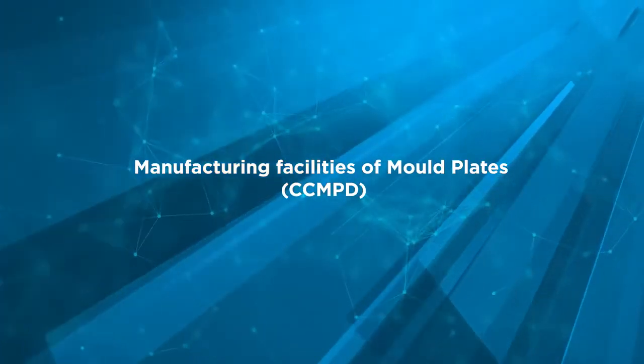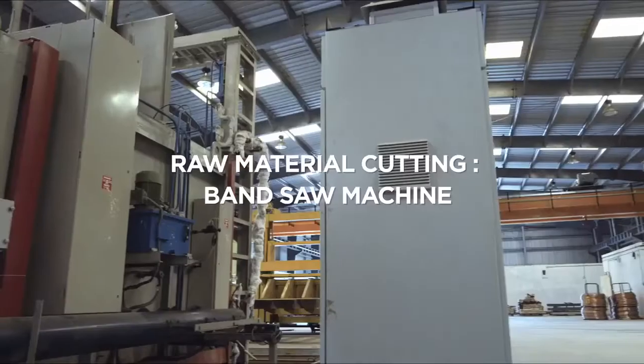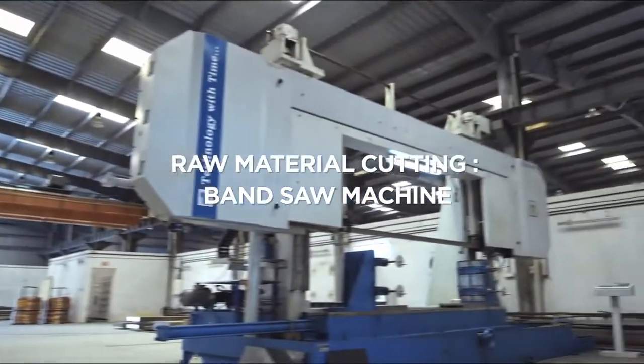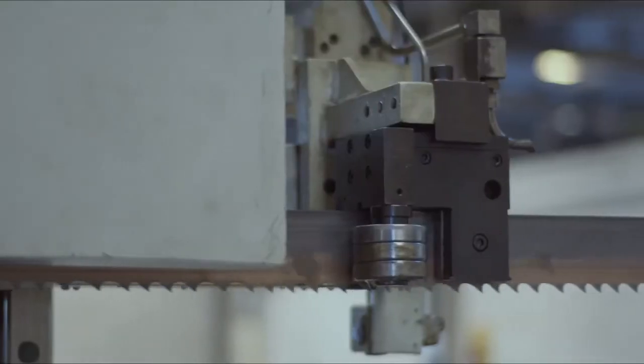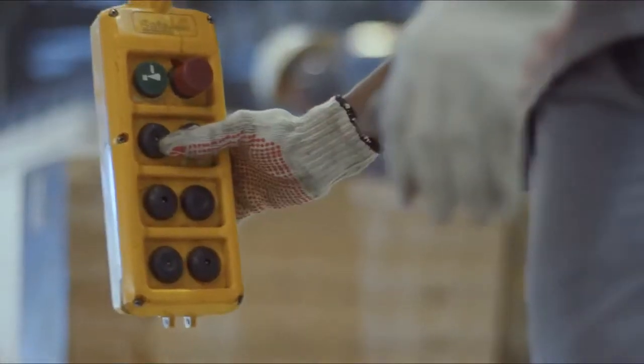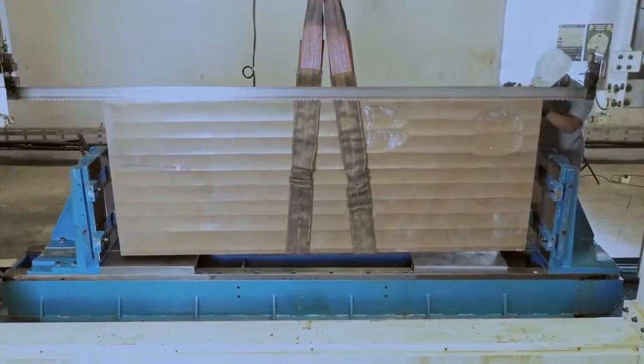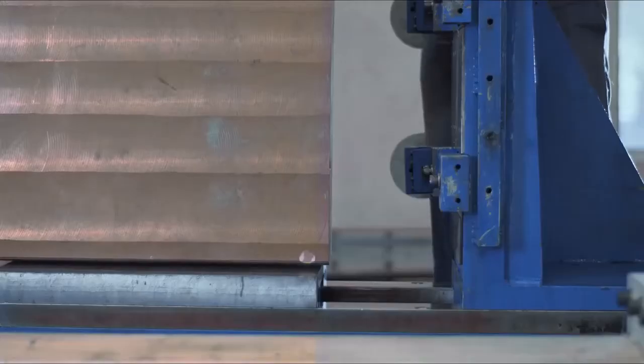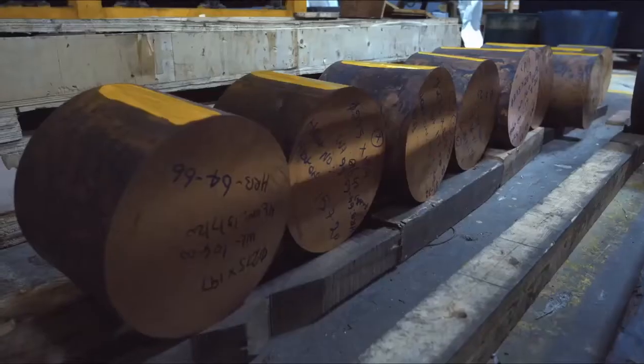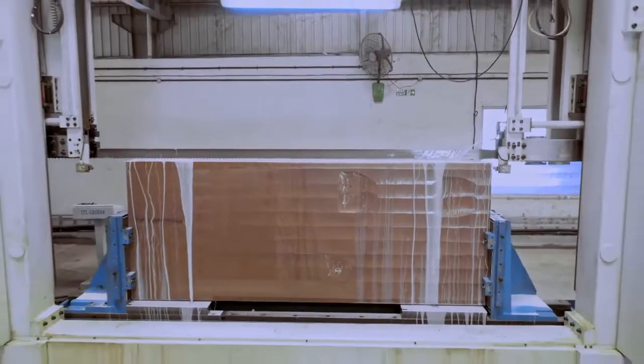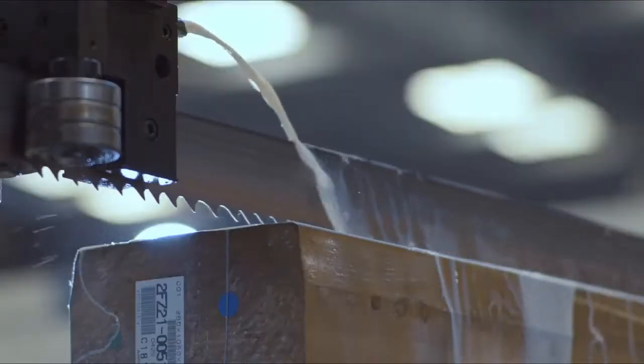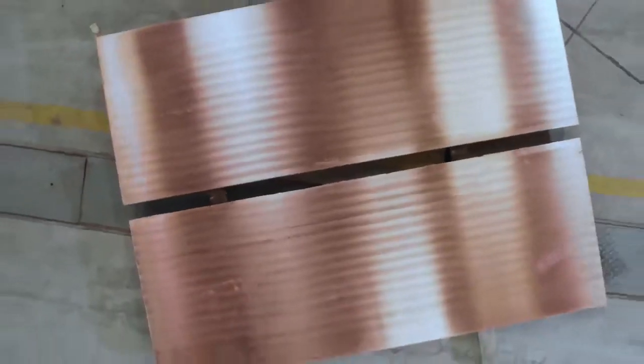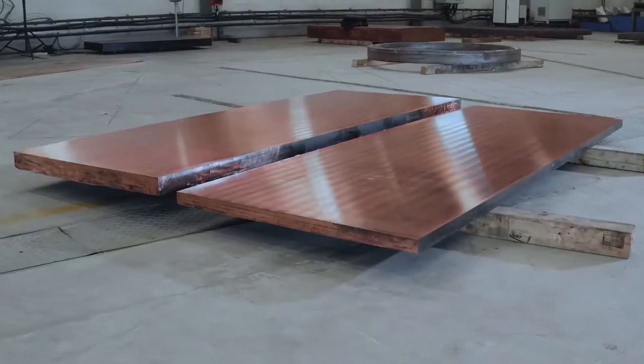Manufacturing facilities of mould plates, CCMPD. Mipalloy has the largest horizontal bandsaw in India to cut large cakes. Our horizontal bandsaw is fully automated and can handle a block size of 3000 mm by 1100 mm and billet size of diameter 1.1 meters. We can cut the materials both before and after heat treatment in annealed and hardened condition as per customer requirement. These cakes are cut with minimum taper and minimum wastage.